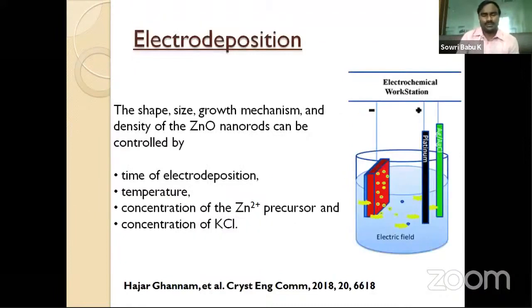So in my work, what we have done recently is we have used the electrodeposition technique to grow zinc oxide nanorods on flexible substrates, that means plastic substrates. These substrates are ITO coated polyethylene terephthalate, PET. They are called ITO/PET. Okay. So the advantage of this electrochemical deposition is you can vary the aspect ratio, I mean, the length and diameter of the nanorod, simply by changing the time of deposition or temperature or concentration of precursors, that is zinc nitrate or potassium chloride.